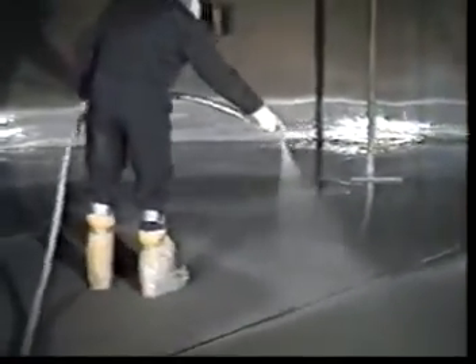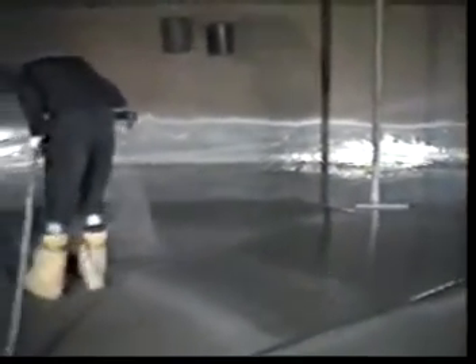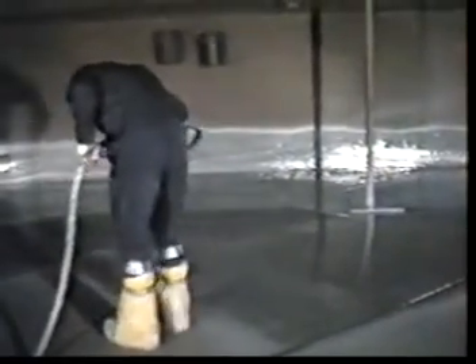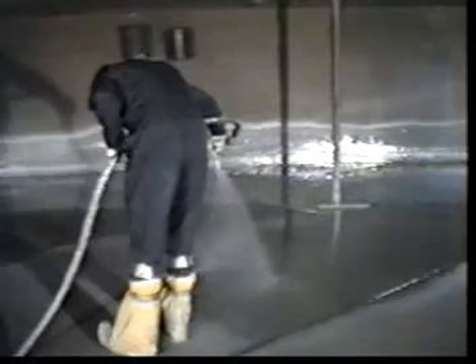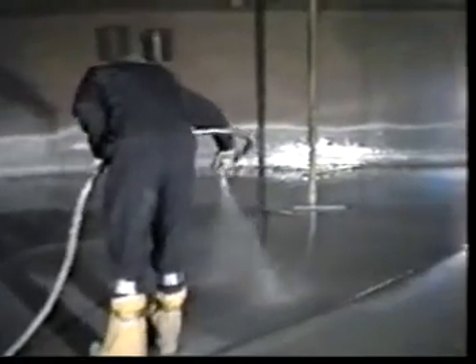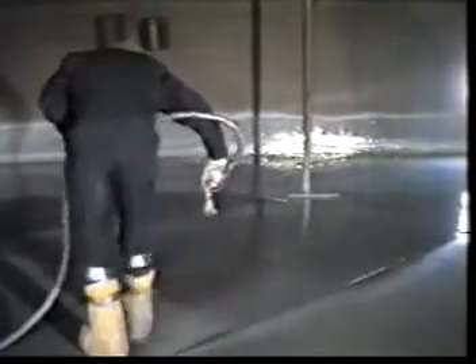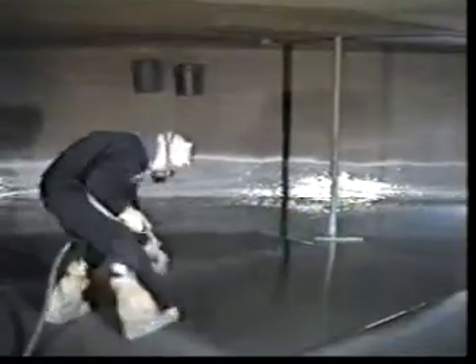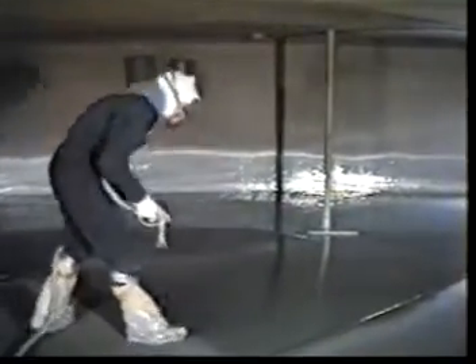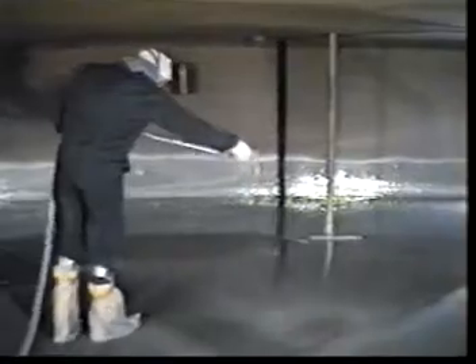As you see, he sprayed the weld area first, and that's to assure that there's good coverage on the weld, because your failures usually are taking place at your weld. And our millage on the weld area, after we've sprayed the tank out, has been running between 35 to 45 mils on the weld areas. And you can see now that he's taking his mill readings. And he does that immediately, so there's a flow back in the material in the areas that he's checked. You can see that disappearing.